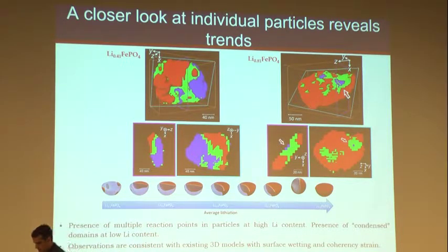So this makes us think that some of the observations that we're making here have to do with the fact that these particles are in an architecture. They're not supplied by electrons and ions the same way. We have carbon, and carbon doesn't touch this whole particle. It may touch an end of the particle. So think of it as a problem of wiring. They're not wired perfectly, and if they're not wired perfectly, you may have points in your particle that are reacting more than others. Based on the theory that was developed and our observations, that's what we concluded.